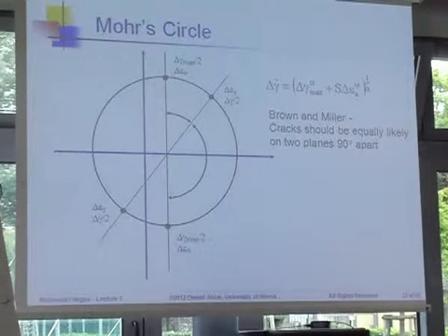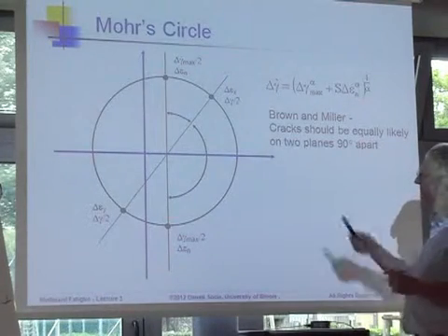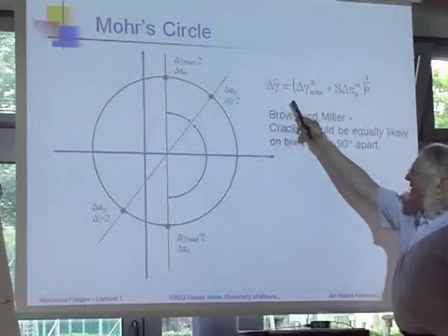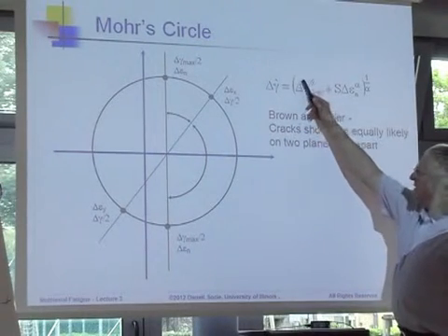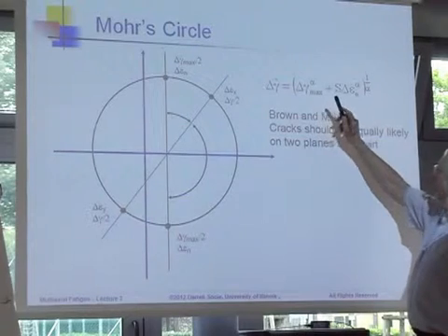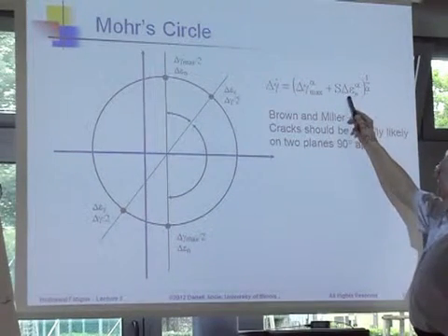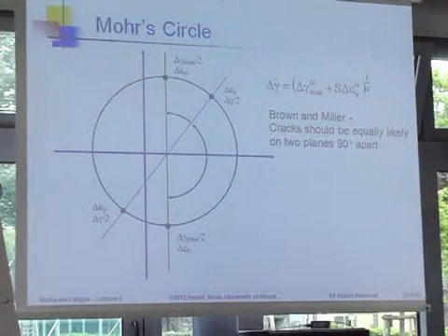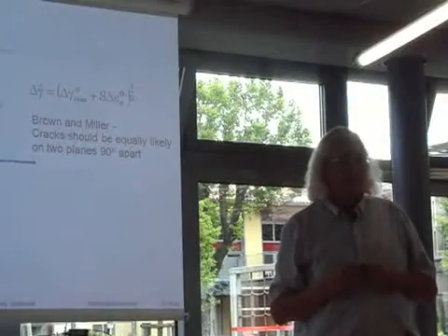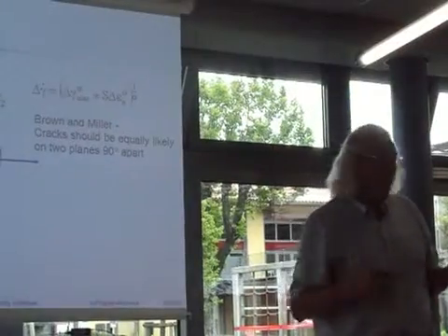And it didn't take very long before they changed their theory a little bit. They changed their theory to look like all other fatigue theories. And they said that there's an equivalent shear strain, and the equivalent shear strain is a function of the maximum shear strain range and the normal strain range, and two different factors here. Right? I've also never understood why they did this. Normally when somebody makes a proposal and they write their first paper, they have a first order model. And then when they need a second paper to go to a nice conference, then they have a second order model. Right? They started off with the second order model.